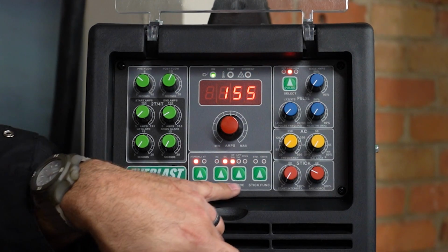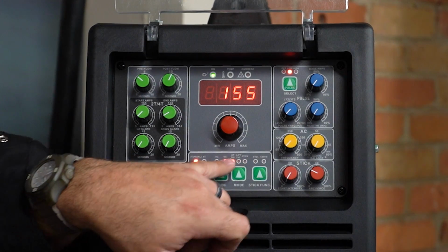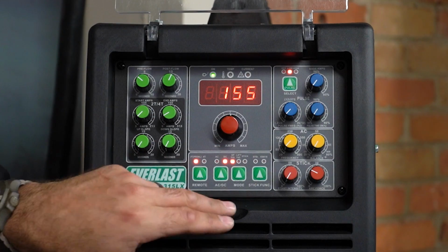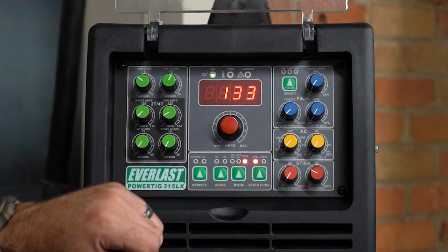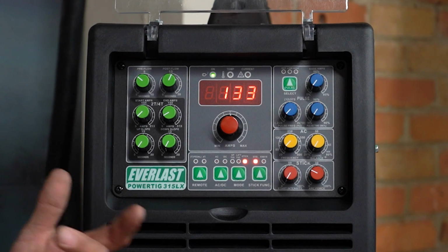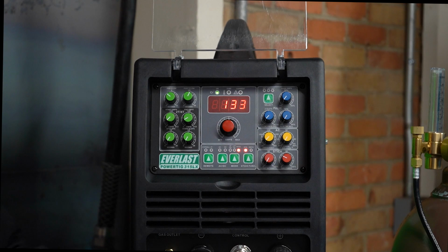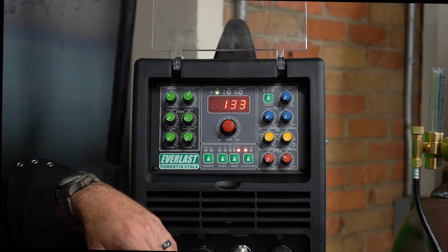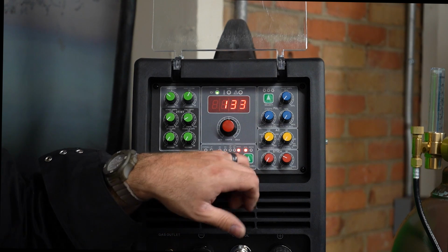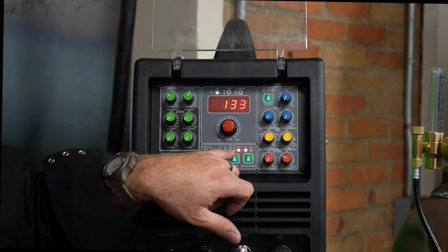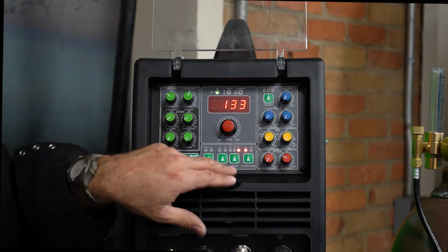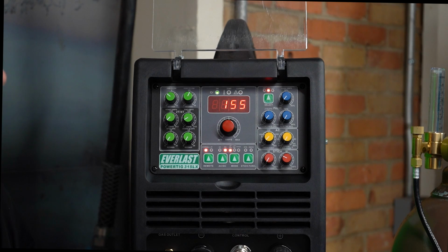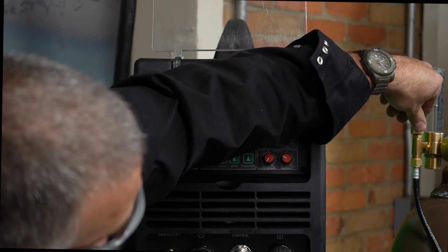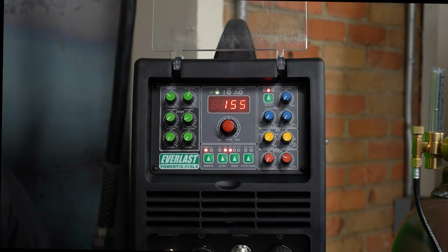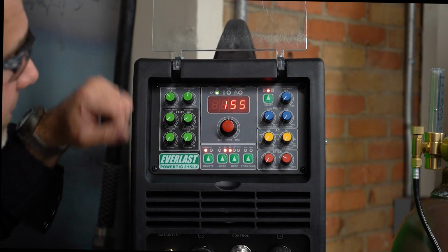Now, if you're on remote and high frequency or lift arc TIG, in this case we're using high frequency, I want to show you something though. If we switch over to the stick welding and I hit the pedal, the gas valve does not open, so I cannot check this regulator. So if you're not able to get your regulator to set, make sure that you are using the proper high frequency TIG setting, because without that, you don't get any gas to flow. And so we want to make sure we get our gas flow about 18 to 20 CFH for the cup that we're using here. I got my pre-flow, I got my post-flow.